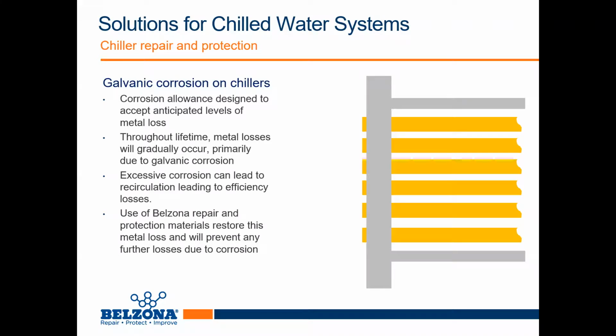So a corrosion allowance is designed to accept anticipated levels of metal loss. However, throughout the lifetime, the metal loss will gradually occur, primarily due to galvanic corrosion. If the corrosion allowance is exceeded and gaps appear, recirculation can occur, leading to efficiency loss, as well as the processed fluid can erode the metal further, accelerating degradation if corrosion is already present. The affected section is always going to be rebuilt using Belzona's 2-component repair composites. It's a paste grade material that rebuilds the substrate to its original tolerance.